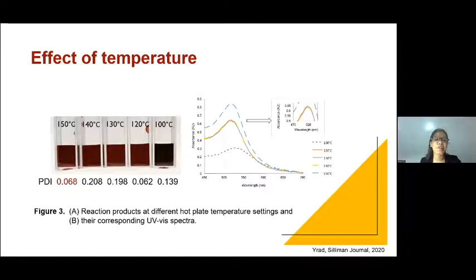Figure 3 shows the reaction product at different hot plate temperature settings and their corresponding UV spectra. Among the trials, only the 150 degrees Celsius setting of the hot plate exhibited the characteristic ruby red. The 100-degree trial was purple, and 140, 130, and 120 are light red.